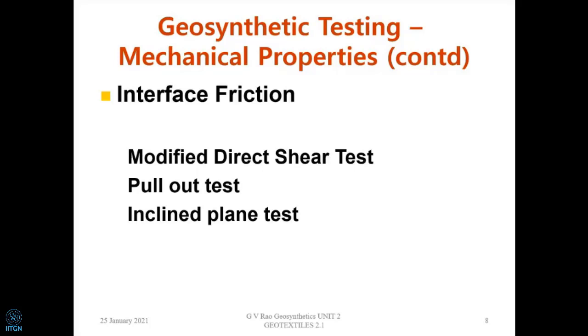There are cases like a GCL where the actual strength values are going to be very, very low, I mean, the angle of shear resistance. In normal soil, yes, we have angles which are usually more than 30 degrees. Whereas when you think of a GCL, what is the angle of shear resistance of a bentonite clay? It will be hardly a few degrees. It may be 3, 4, 5, 6 degrees.